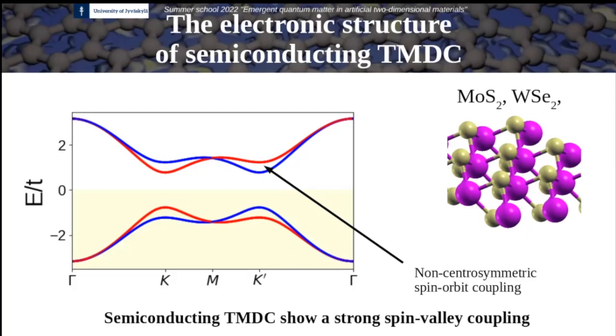And in particular, this spin splitting that they have here is maybe one of the most important properties of transition metal dichalcogenides. This spin splitting allows you to excite electrons in one valley or in the other valley if you are capable of coupling the spatial degrees of freedom to the spin. So if you shine circularly polarized light on these dichalcogenides, we are capable of exciting electrons in one valley or in the other valley, which is, of course, extremely important for valleytronic applications in two-dimensional materials.